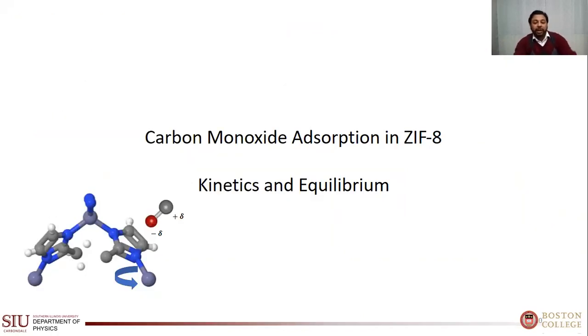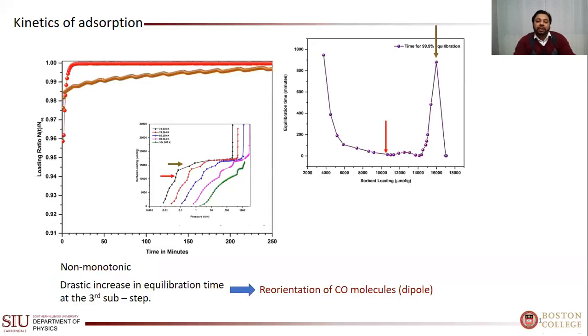So we have done 3 main projects on ZIF-8, and we started by introducing carbon monoxide, which is a dipole molecule, to see whether ZIF-8 can absorb carbon monoxide, because that's another important application. And if it is absorbing carbon monoxide, how efficient is that? We figured out that the carbon monoxide also triggered the linker rotation because of the dipole interaction between the carbon monoxide and the linkers, so it rotates, and the carbon monoxide can be easily absorbed inside the material. So it's a good material to absorb carbon monoxide, which is a pollutant and a toxic gas.